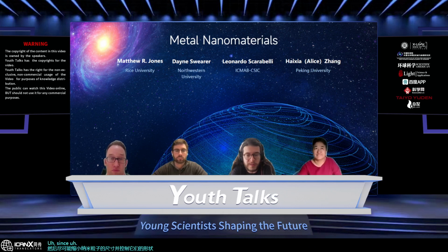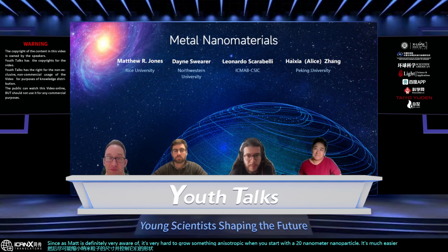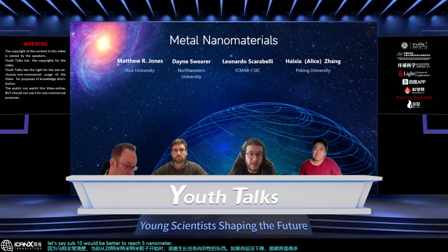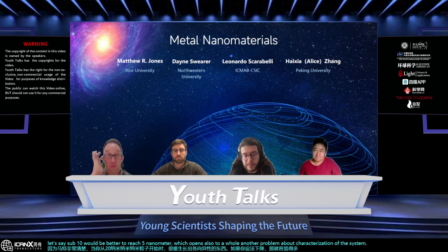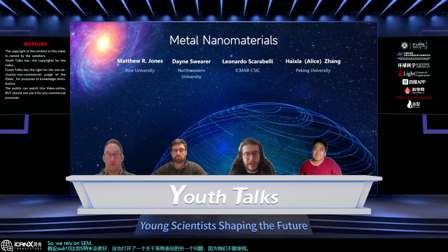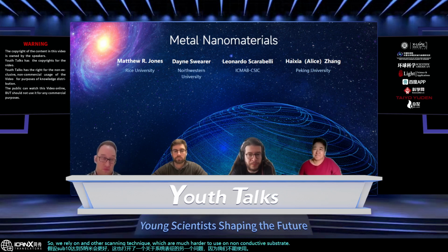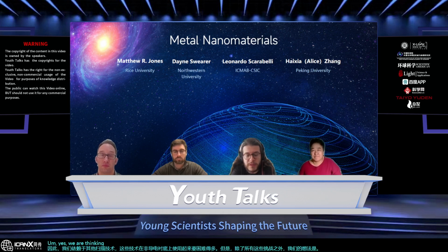Since, as Matt is definitely very aware of, it's very hard to grow something anisotropic when you start with a 20 nanometer nanoparticle. It's much easier if you manage to go down to, let's say, sub 10. It would be better to reach 5 nanometers. Which opens up a whole other problem about characterization of the system, because we cannot use TEM, so we rely on SEM and other scanning techniques, which are much harder to use on non-conductive substrates.